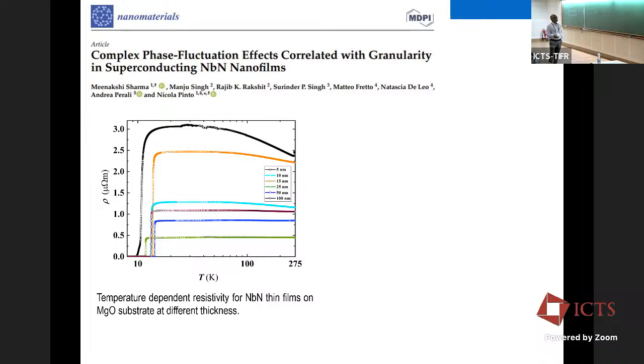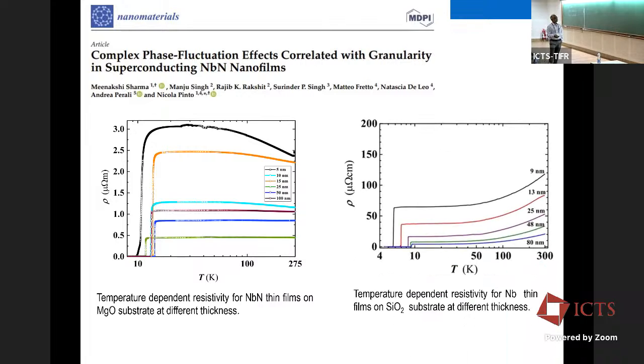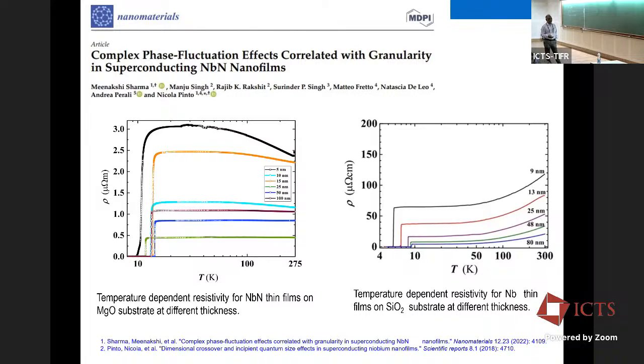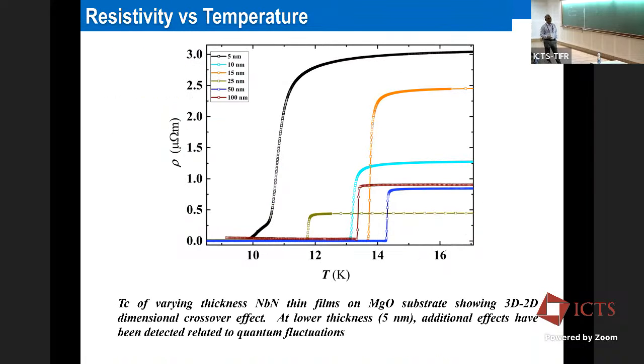If we compare this with the Nb thin film on SiO2, here you can see we are having a broader transition. We are having some delta TC in here, where the transition in the case of NbN on MgO is pretty good. So some other factors are also playing some role in there. And now you can see clearly that in the bulk, when we are having 100 nanometer or 50 nanometer thin film, we are getting up to this